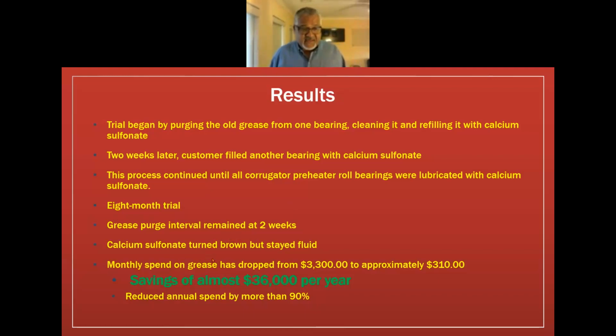The calcium sulfonate grease at those temperatures will turn brown, and it turned brown, but it stayed fluid. That was really impressive to the operators, because with a fluid grease versus a clumpy grease, you're going to have lower operating temperatures by nature. So the mechanics loved the fluid condition of the grease. It stayed fluid. It didn't cake up.